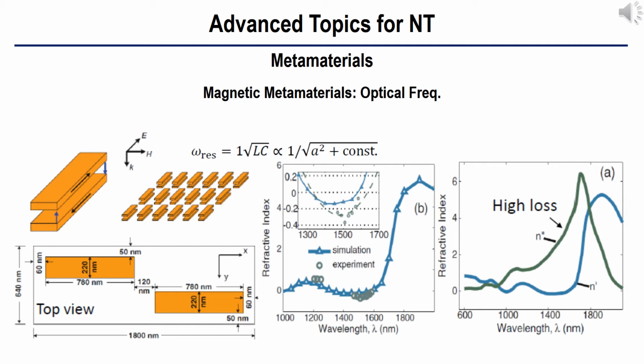For example, we can think of new geometries such as paired nanorods with a lattice constant of 1 or 2 micrometers and fishnet lattice-like structures. In addition, we can think of a metal strips array as shown in the left figure. In this structure, we can expect a resonant magnetic response as a function of metal strip width. For example, broader metal strips provide negative magnetic permeability for antisymmetric currents. However, there is a non-resonant electric response. Therefore, narrower metal strips can act as a diluted metal with negative electric permittivity as shown in the right plots.